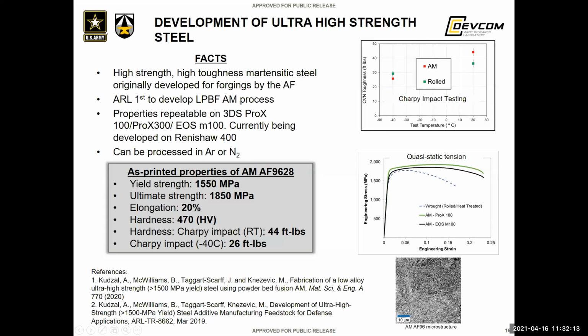You can see here that the mechanical properties from our small scale testing actually outdid those of the rolled and heat treated version of the same material. The same goes for Charpy impact testing at room temperature. It was actually better than that of the rolled material. And at -40, it was fairly close. And then we had pretty good elongation at about 20%.